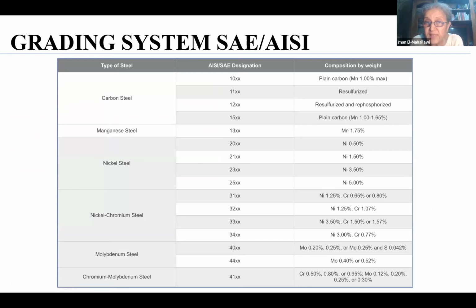Of course, each one of them has a certain range, as I have just mentioned, for the alloying elements. When we say manganese steels or nickel chromium, there is a range, and these ranges are all available in the standard specifications. And now we can understand why we have limitations on these ranges, because we obtain the benefit that we are looking for through this designated range. However, in this context, I would like to say that maybe the standards should be revised during the next decades, because the steel industry has moved from producing steels from raw iron to using recycled steel, and recycled steel is usually associated with some deviations in these contents and ranges. And still, it's a very hard decision.